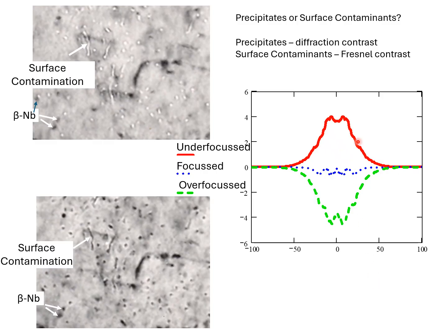If we vary the distance slightly, by a fraction of a nanometer, in this particular case we go to a condition where we have a bright peak, like here, or a dark image, as we have here. And at the point of focus, there is very little intensity.